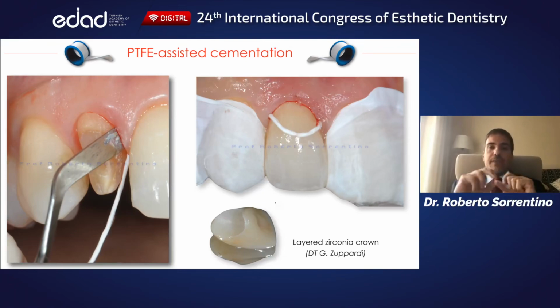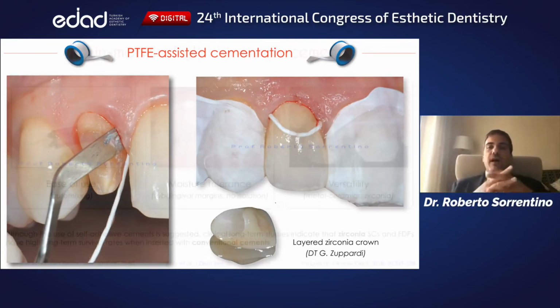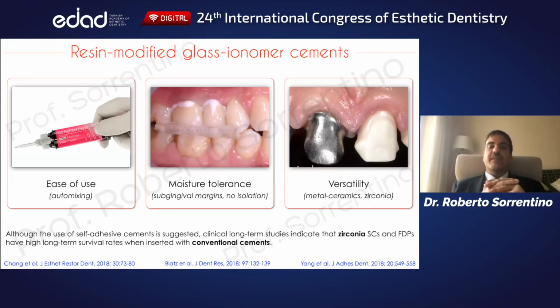If you have to manage full crowns, a valid alternative to purely adhesive techniques is represented by resin-modified glass ionomer cements, user-friendly luting agents that tolerate wet contamination, can be used without strict isolation, and are really versatile since they are suitable with different materials, like metal ceramics and zirconia. Hybrid cements are particularly useful in case of subgingival margins.